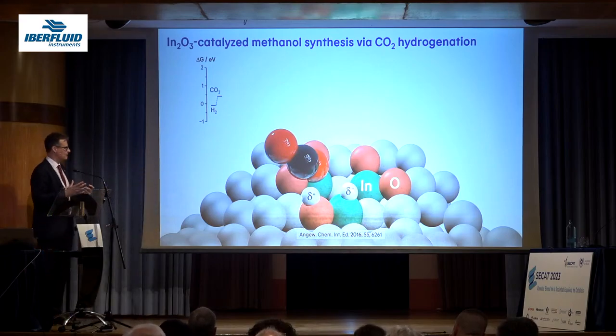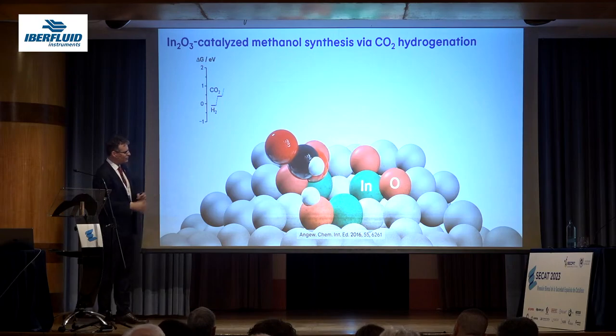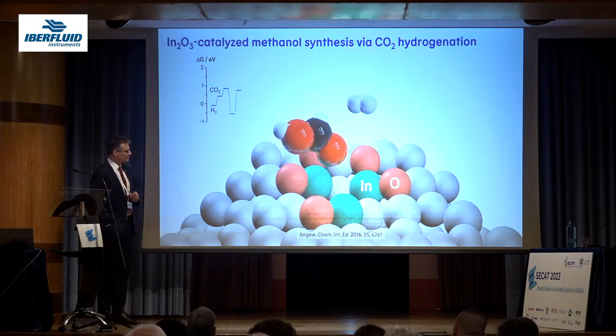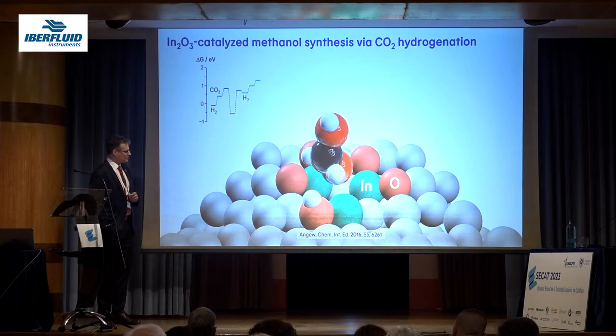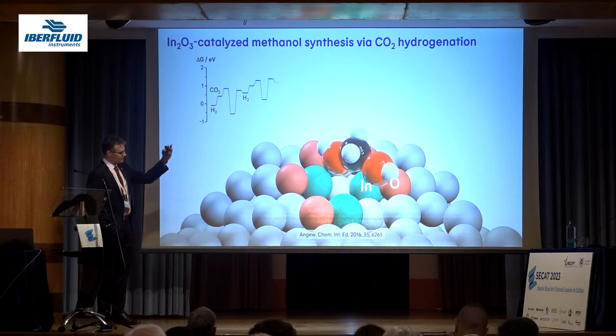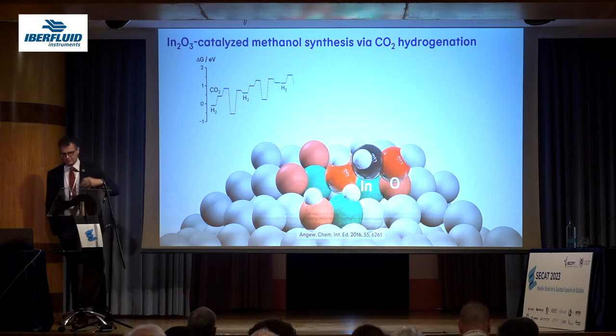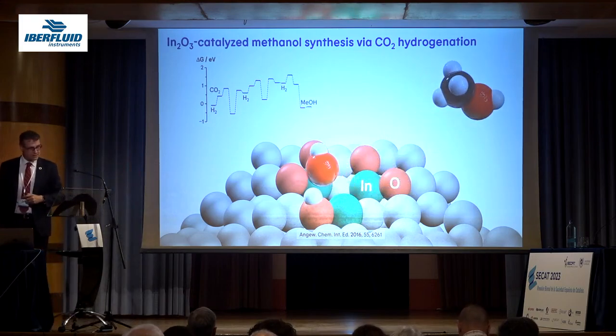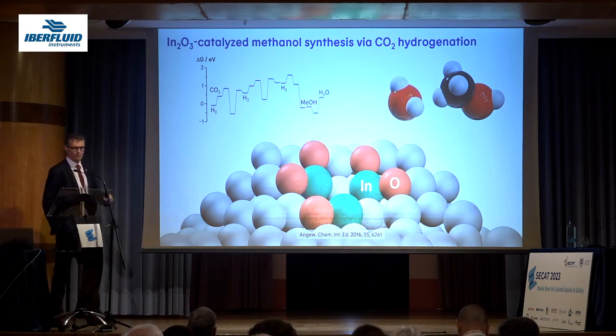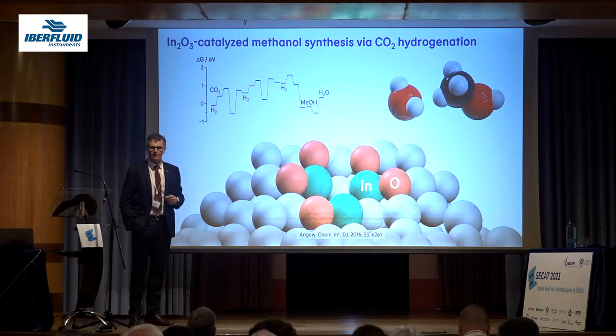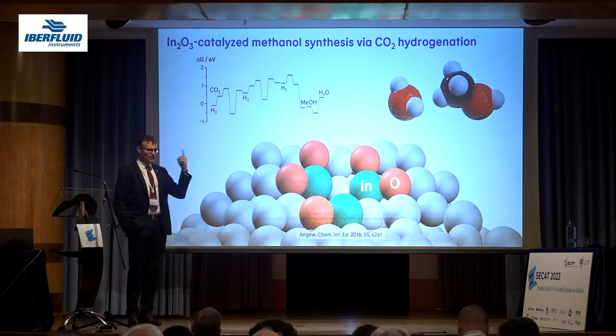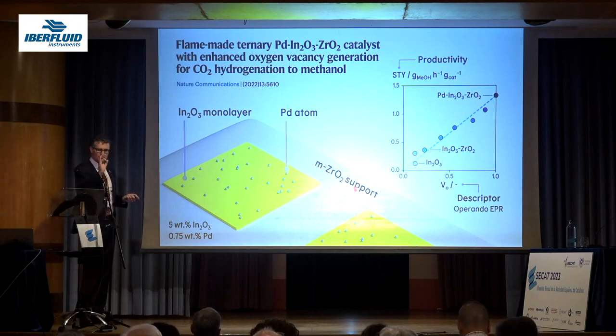I'm not going to extend myself very much, but this is a little bit how it works. You have heterolytic activation of hydrogen. It happens 3 times, so 3 moles of hydrogen activate, and then this is a cartoon of how the reaction mechanism takes place, with the energy profile where you form CO2, methanol, and water. And of course, a real industrial catalyst, as I said before, is not a single crystal, is not a mono-component material. It is an architecture of many different materials, right? So here you have a very unique, very singular architecture.